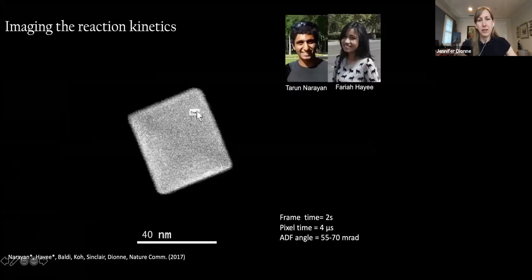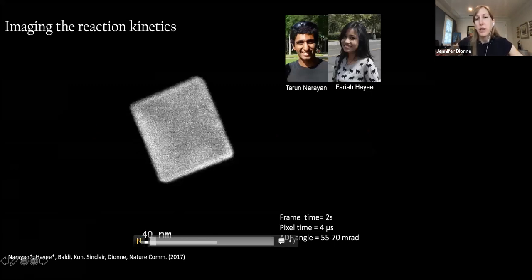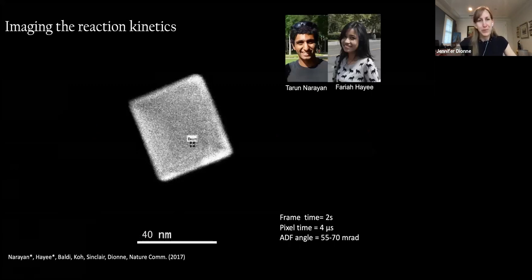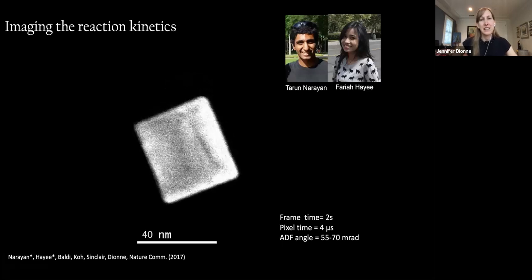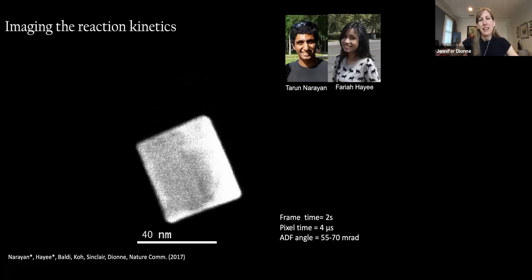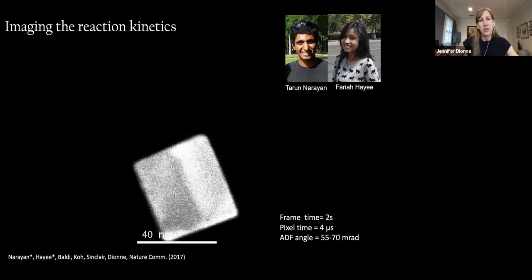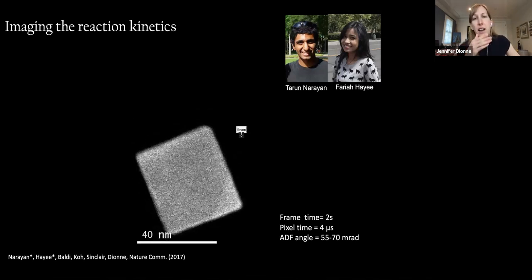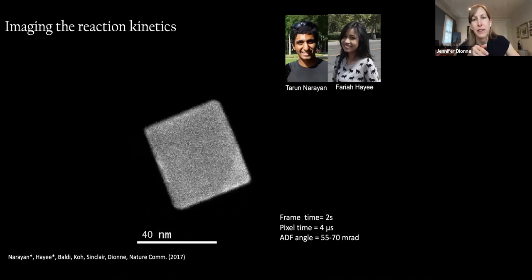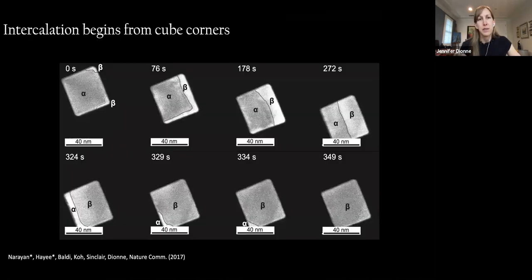So everything I've discussed so far is in equilibrium. How can we image the reaction kinetics? Well, there we can rely on STEM and EELS contrast. And here, when hydrogen has been introduced into the chamber, you can see that the contrast of this individual nanocube has changed. If we look just at some time snapshots of that moving, we can actually identify that contrast as where hydrogen is intercalating, by combining not only the STEM contrast with diffraction and local EELS studies.